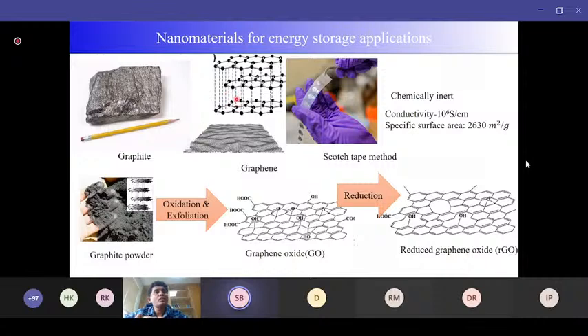And if you look at the construction of the graphite, it contains several individual single layers of carbon. These individual layers are known as the graphene, and they can be separated by a simple scotch tape method. You put on some tape and you do the scotch taping several times. You can separate it, and the importance of these materials is that they have a very high surface area.